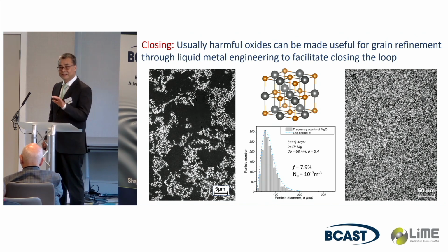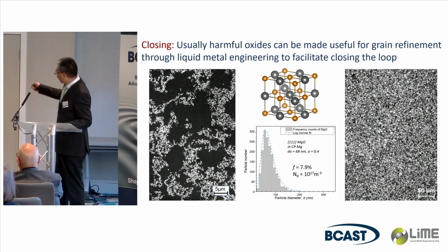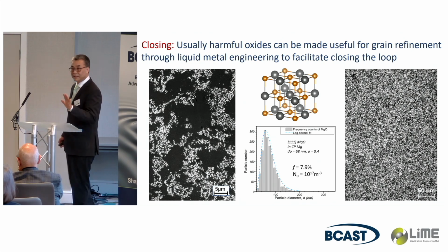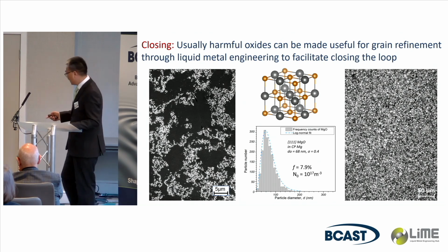They can supply seeds for nucleation, for grain refinement. And I just show here, look here, this is real magnesium, okay? You can achieve this sort of fine and uniform structure by high shear only, no grain refiner at all.